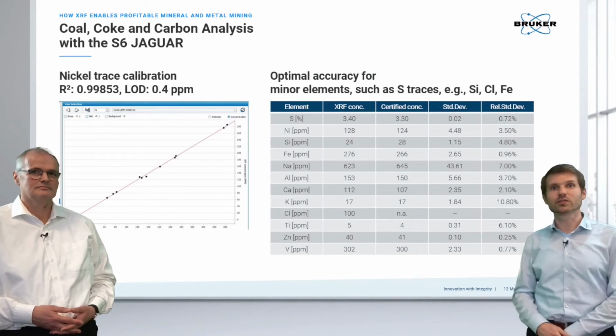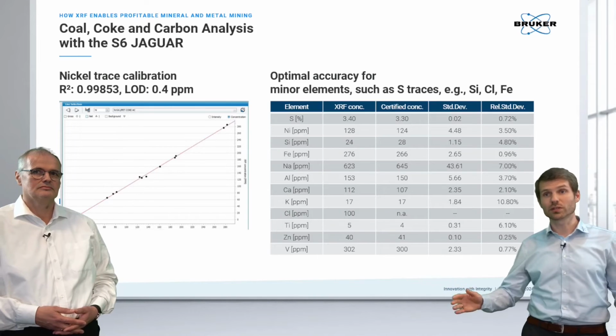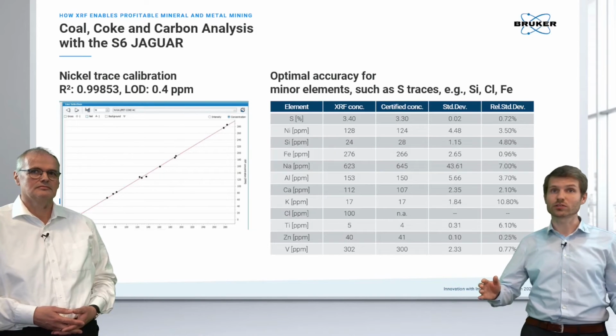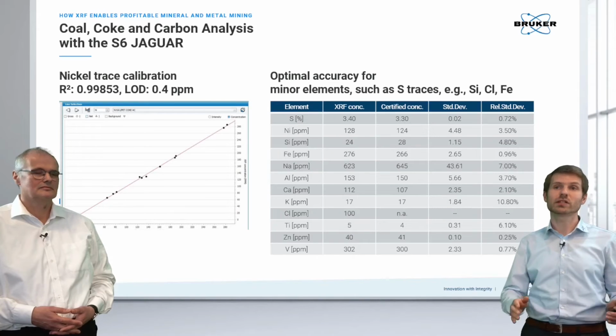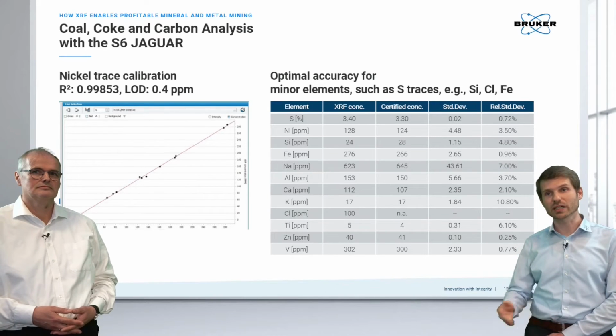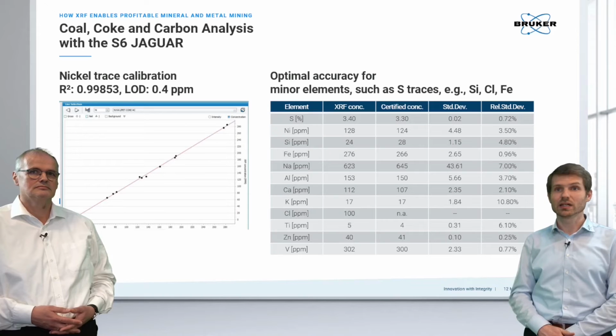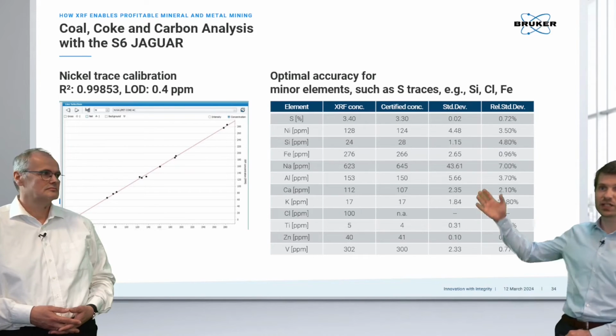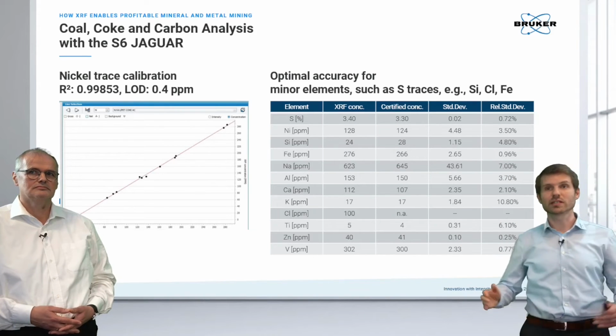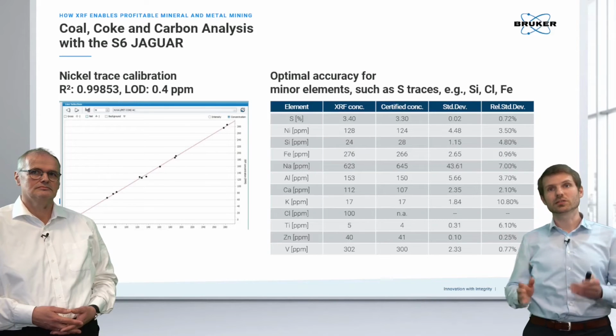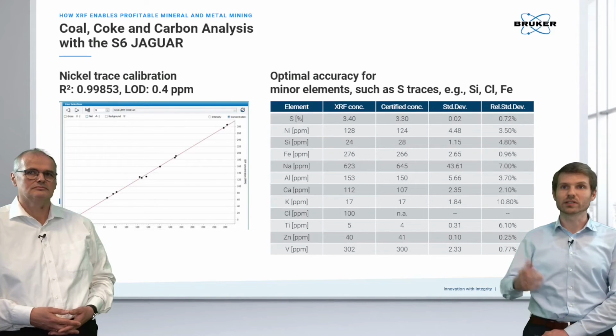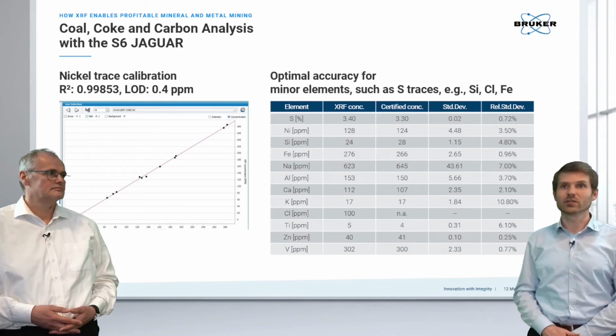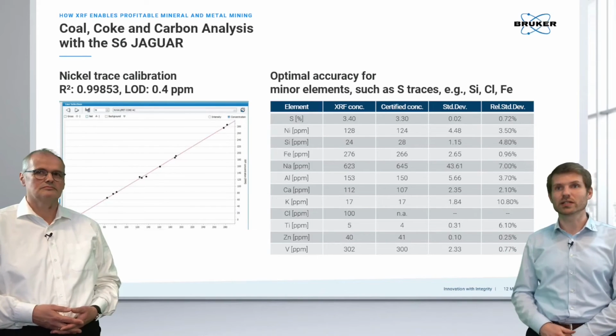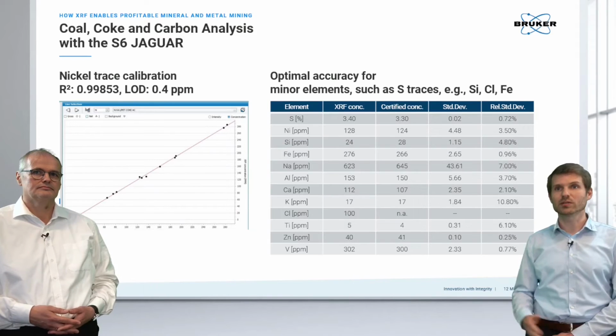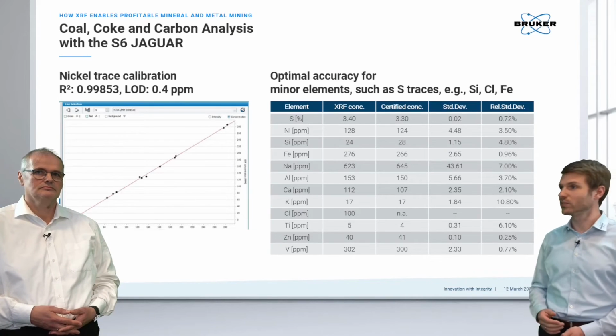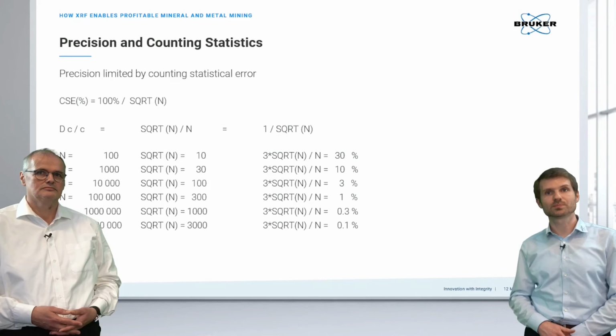On Kai's side of the screen, you see a correlation curve for nickel, which is an important trace element also to cover, where we get with a benchtop wavelength dispersive system down to a lower limit of detection of 0.4 ppm. So this is really extraordinary. And if you digest these tables here, you can essentially see that we are matching the certified value quite closely. For example, here in nickel, we are very close to the concentration of the certified value of 128 ppm to 124 ppm, and with a high precision. This is done with the S6 Jaguar.